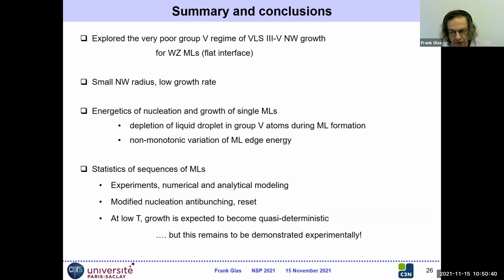But this requires the relatively large monolayer edge energy, so that this non-monotonous behavior and this negative derivative of the edge energy is sufficient compared with the chemical potential. So it becomes interesting to add new atoms to the monolayer, because then you decrease the total edge energy. But obviously, for this to be interesting for the system, this energy has to be large enough. If we only have a small edge energy, then this will not be sufficient. But I would predict that if this energy is sufficient, and for this nanowire, then it becomes possible that we deplete the liquid below equilibrium with the solid, even with the bulk solid.